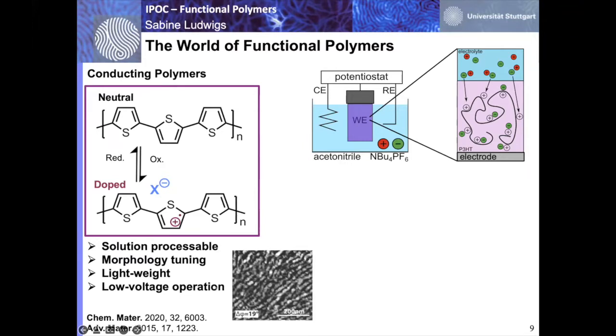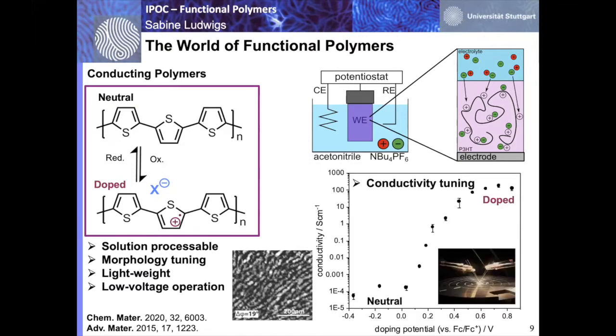One of the highlights of my group was, for example, that we could tune the conductivity of such polymers by changing the doping potentials during electrochemical experiments. And what you see here, when you look at the conductivity on the Y scale, this polymer is kind of neutral at normal conditions, and then it would be in this form. When you dope it, then you reach around 200 Siemens per centimeter, which is already good.